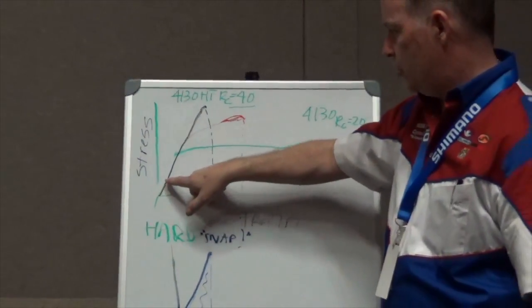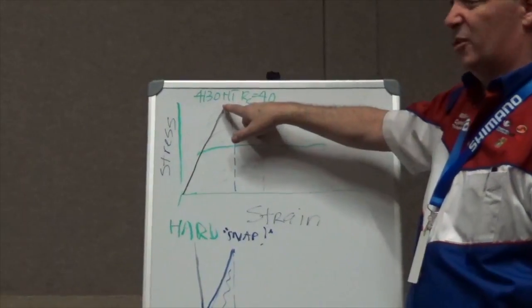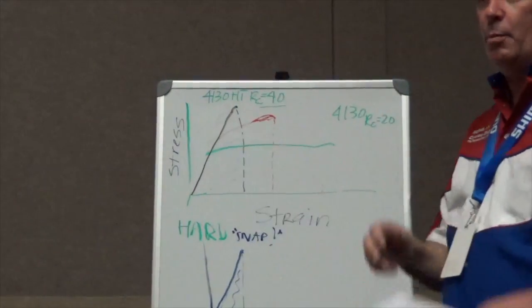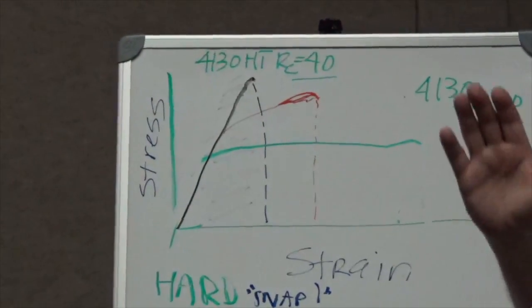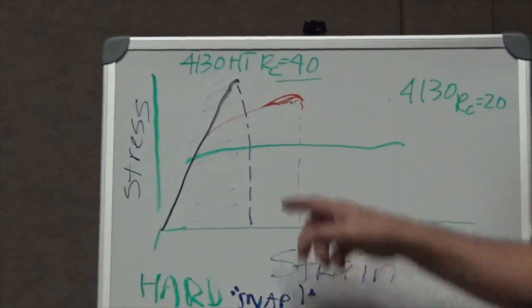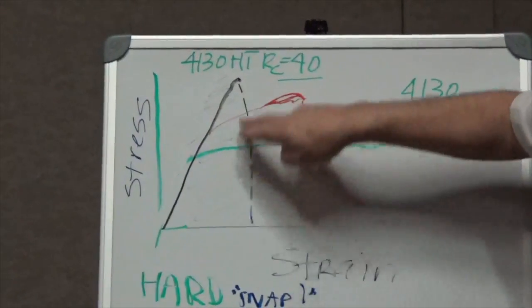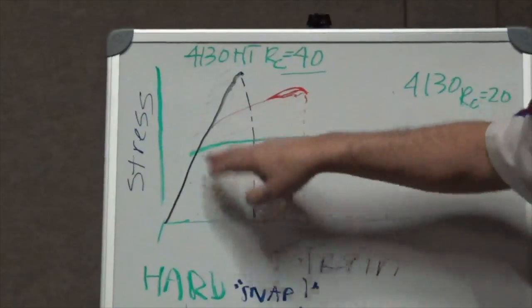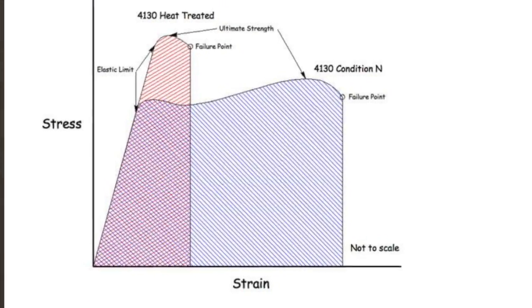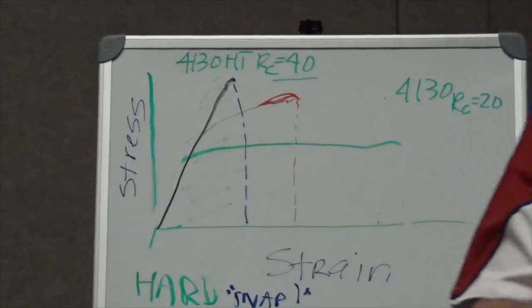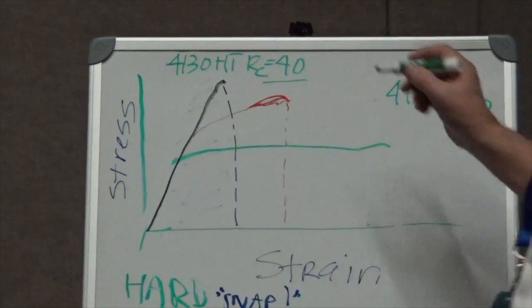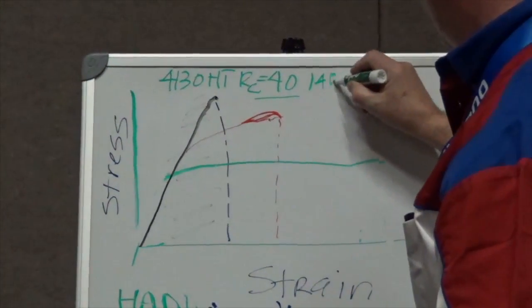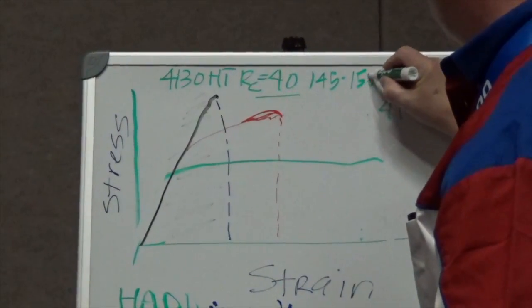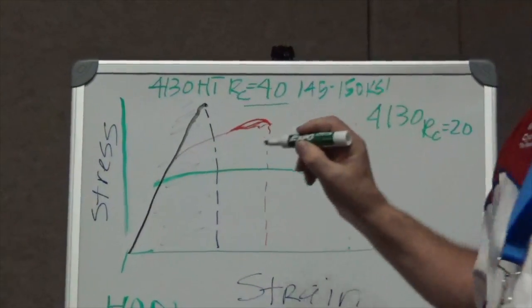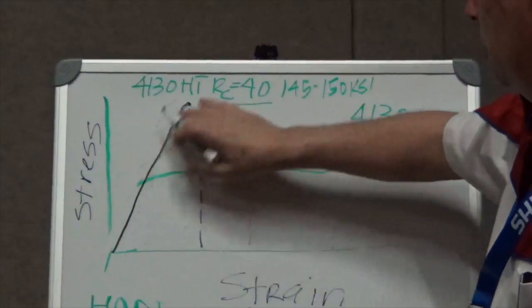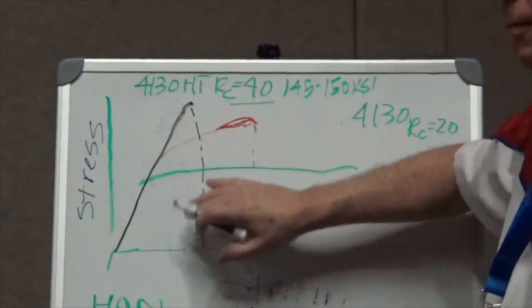Well, if you were to stretch that, it would go, and then it would just go snap. It wouldn't have much of a stretch before it failed. It would just go, and then stop. Well, the total energy underneath this graph, this area, is really the determining factor. The fact that it had a tensile strength of 145 to 150, which is what manufacturers will talk about, can be misleading because the material wasn't actually able to absorb that much energy.